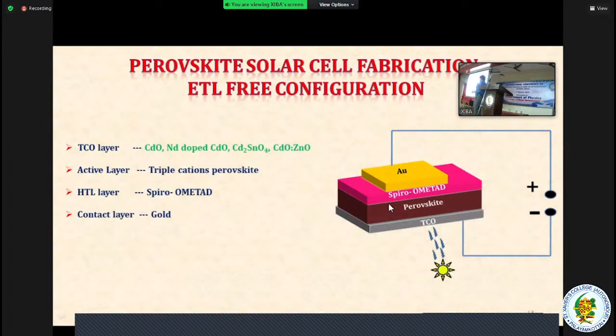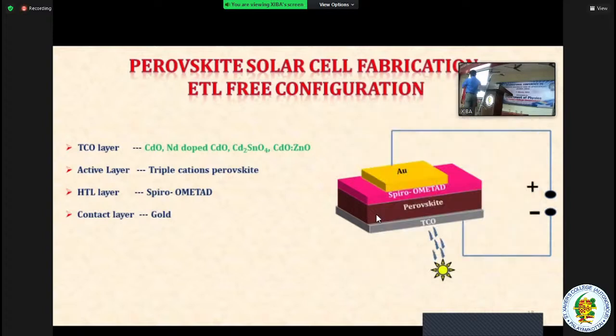In my part, initially we tried with the ETL-free perovskite. We have an ETL-free perovskite solar cell. ETL-free means we have to use the TCO layer, the transparent conducting oxide layer. We use materials such as cadmium oxide, neodymium-doped CdO, cadmium tin oxide, and cadmium zinc oxide.